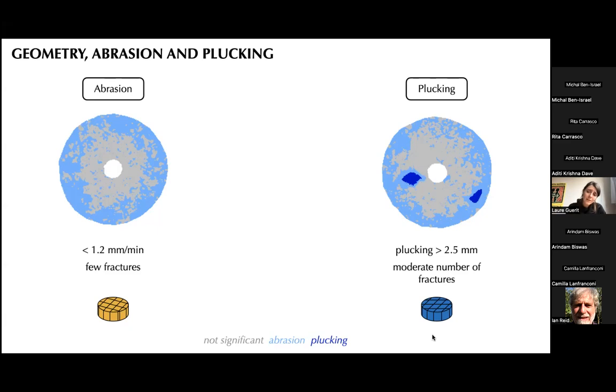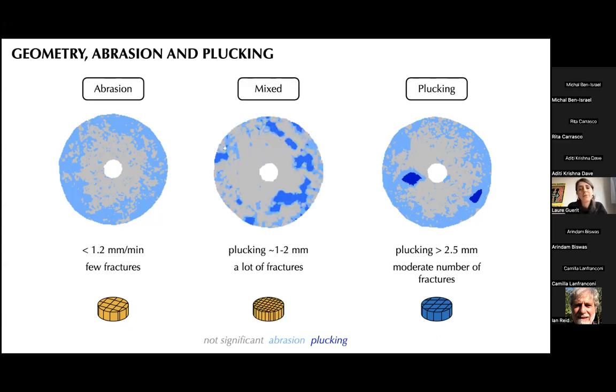And what is very interesting is that we observe a third type of experiment. These experiments are intermediate between these two. So this is the experiment with a dense network. In this case, we do observe some plucking, as you can see with this dark blue spot here, but the thickness of this plucking is limited. It's often 1 millimeter, up to 2 at the maximum. And the plucking is located on the edges, as you can see on this picture. So very similar to what we have in abrasion. So we do have plucking, but in terms of rate and in terms of localization of erosion, they behave as if they were in abrasion.